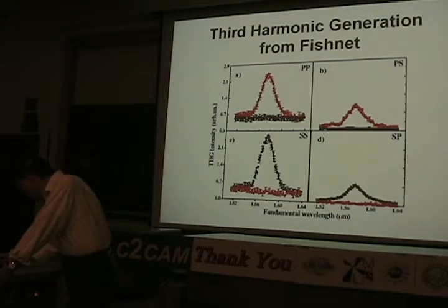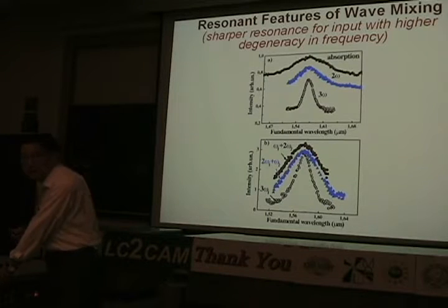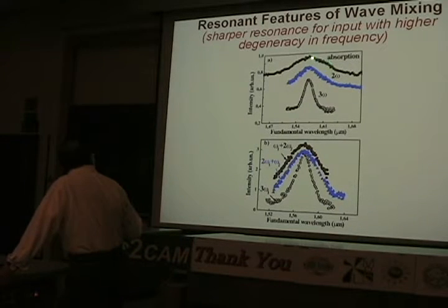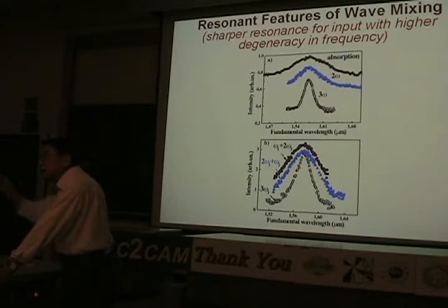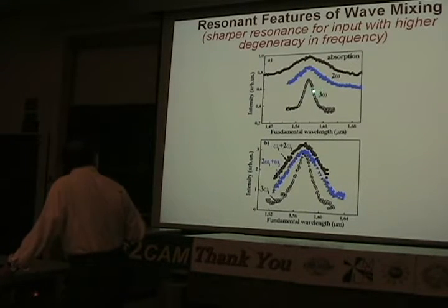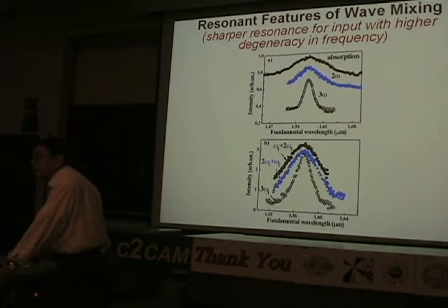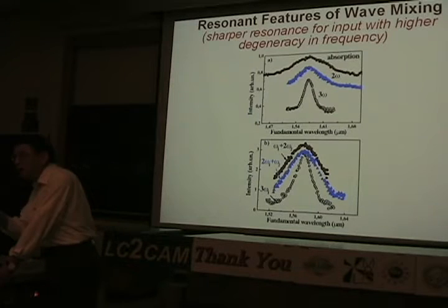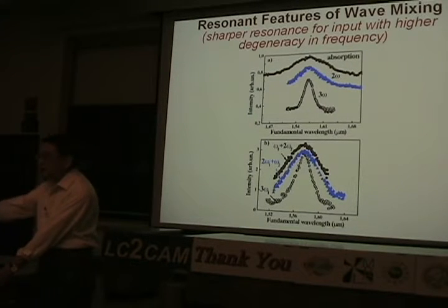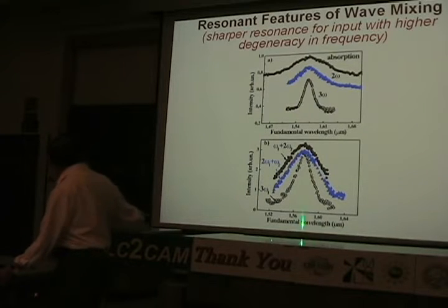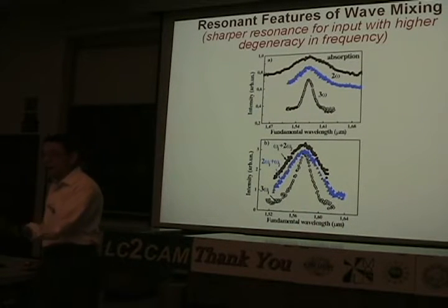And the more interesting thing is if you compare those resonance peaks, you will find in all these cases omega is at resonance. Okay? Now you see 3 omega is sharper than 2 omega, 2 omega is sharper than omega. Also, if we do four-wave mixing, 3 omega is sharper than 2 omega 1 plus omega 2, and then sharper than omega 1 plus 2 omega 2. Okay. So it says, although you have only one resonance, only omega 1 is at resonance, somehow the 3 omega sees a much higher resonant effect.